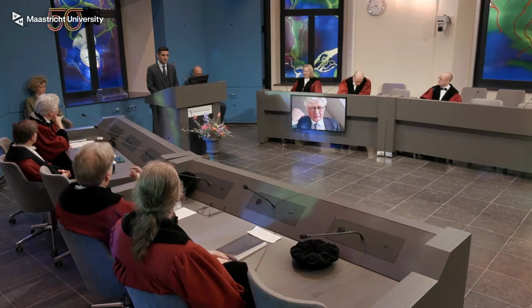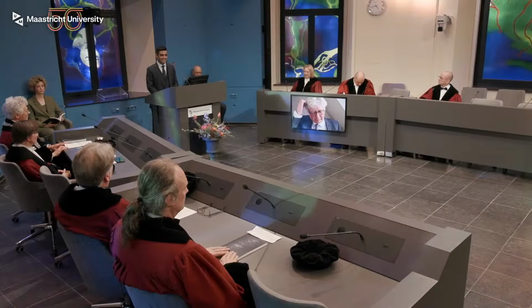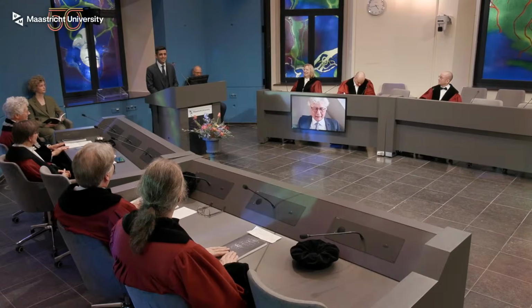And of course, we are doing more ESCR tests nowadays. After my PhD, fortunately, I'm staying as a postdoc in the same group, and we have some ESCR projects going on. And that's the change that I already made to the samples that we are doing right now. We are doing samples with 5 MPa, 6 MPa, to avoid having these effects. But in the first 2 years of my PhD, I really couldn't change the stress there, because they wanted to compare all of their results with each other. You need a bit more time. Yes. And ESCR takes a long time. You know better than me.